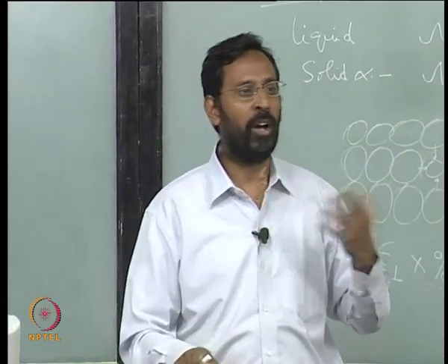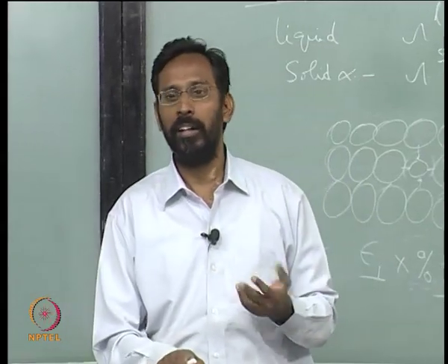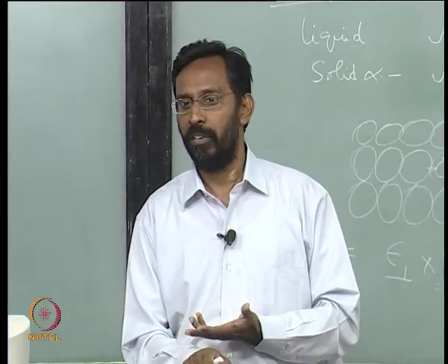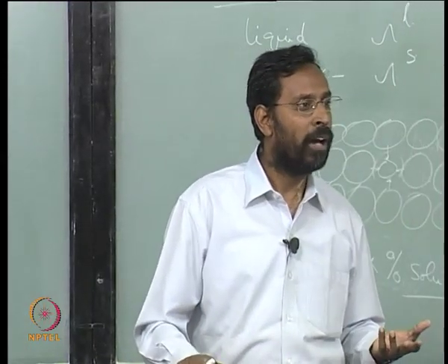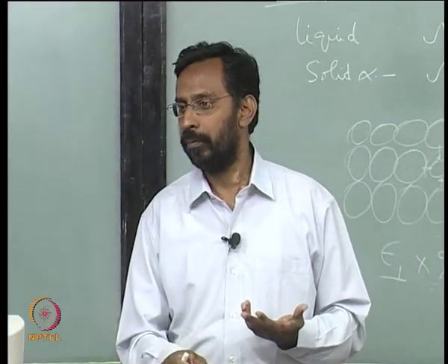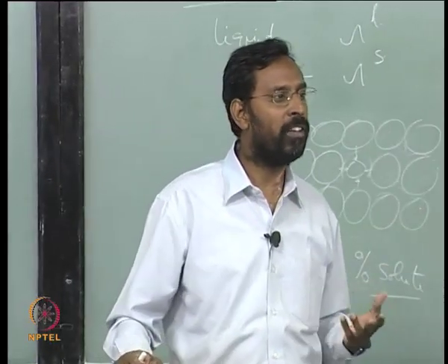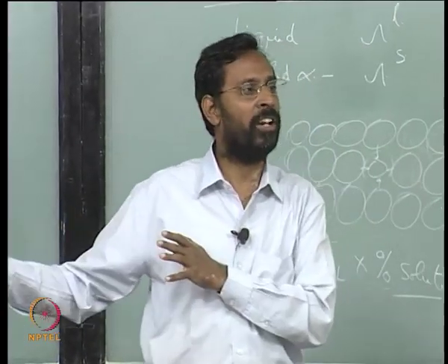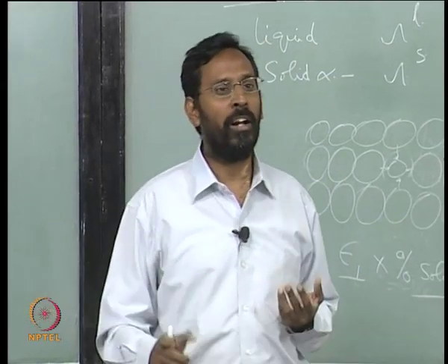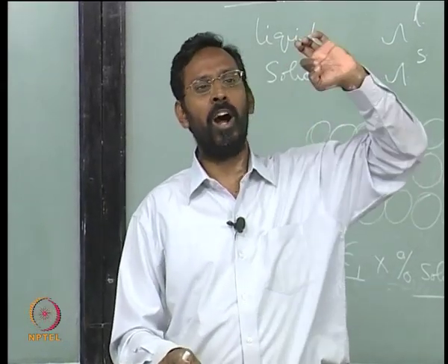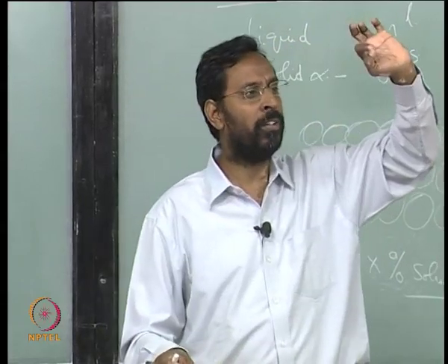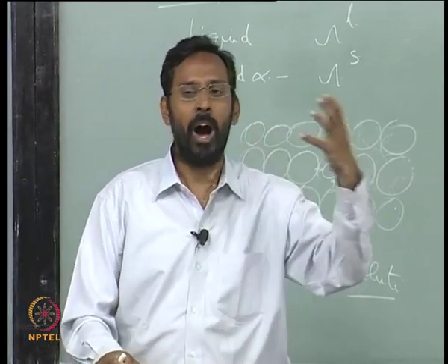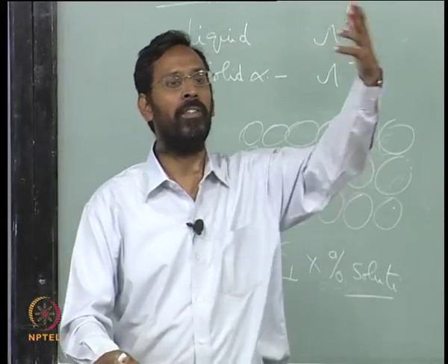structurally ordered. Whenever you talk of disordering, many of you might know that there are two types of disordering we talk about: structural disorder and chemical disorder. So whenever I talk about an ordered compound, I am talking of a chemical order there. When I say structural disorder, it basically means a crystal structure becoming an amorphous structure. That is a structural disorder. When I say chemical disorder, that basically means in a chemically ordered compound, you have specific positions for each of the atoms. Let us say in this Ni3Al, just now I told you that nickel occupies the face centered positions, the aluminum occupies the body corners.